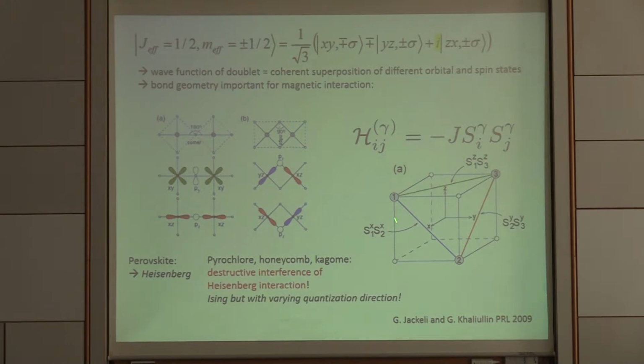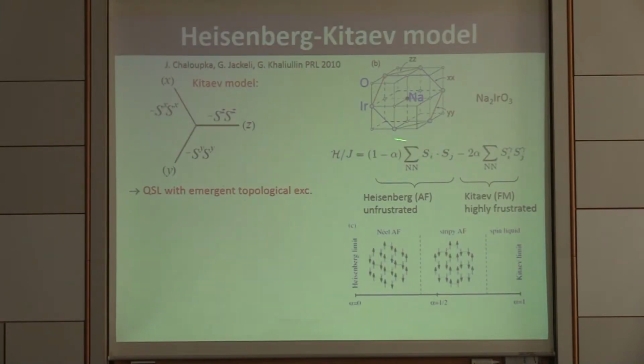And so that gives rise to such a kind of quantum compass, where exchange along different spatial directions couples different spin components. And they also pointed out that we can use such units to build up a honeycomb lattice like realized in sodium iridate, and then we would have along the 3 different bonds a coupling here of the x components, here of the y components, and here of the z components. So that's the ingredient for the honeycomb Kitaev-type model.